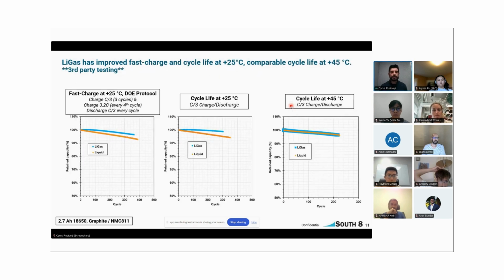This is the same cell package, but now it's third-party data that we are sharing with you today. So we have 2 jelly rolls, both 18650s, one filled with a liquid electrolyte, one filled with LiGas electrolyte. And the liquid electrolyte is just your run-of-the-mill type carbonate-based electrolyte, nothing special there. This is just showing fast charge cycle life, where this is a DOE protocol, I should add. Every 3 cycles, it's a C/3 charge and discharge. Every 4th cycle, it's actually a 3.2C, which is equivalent to an 80% state of charge swing in 15 minutes.